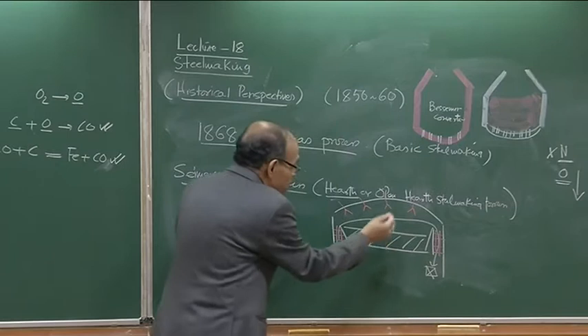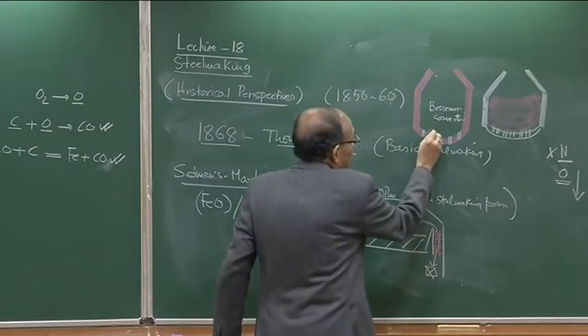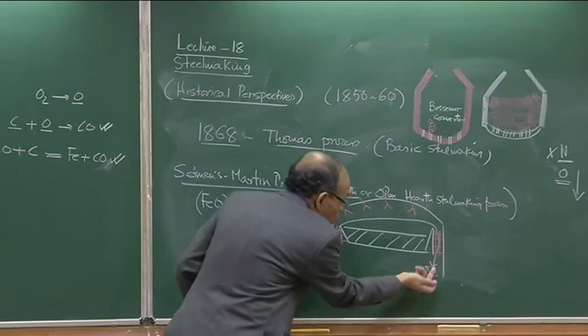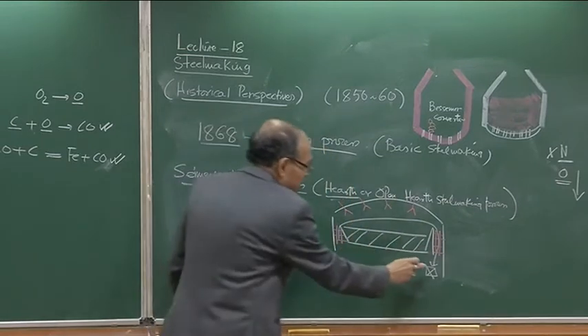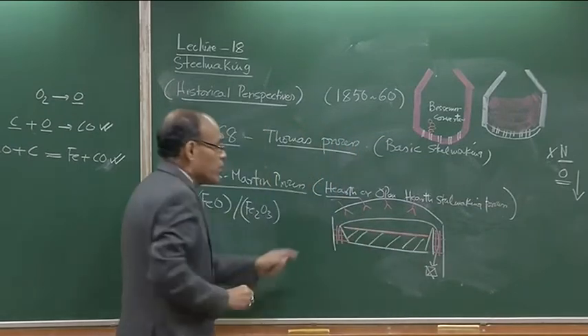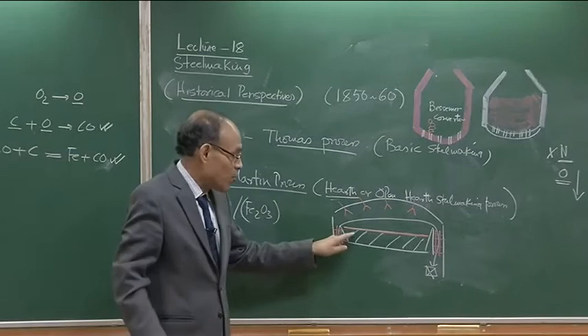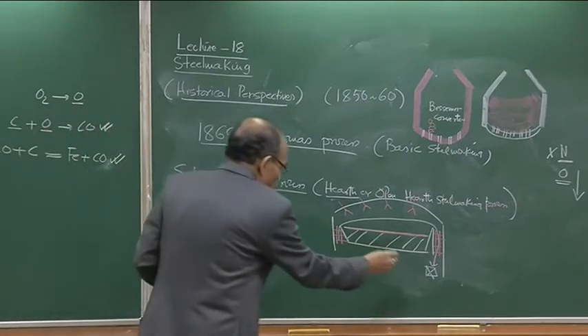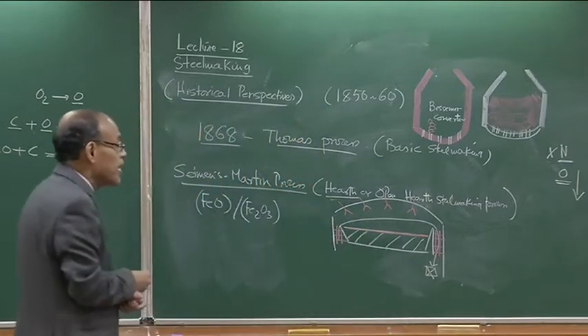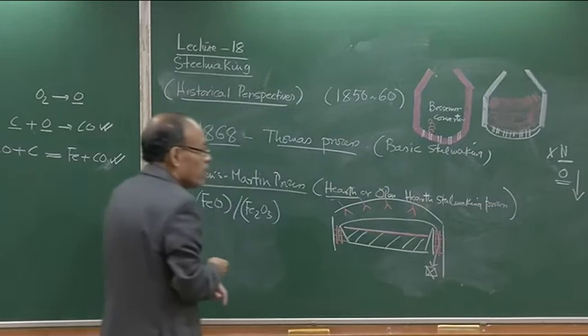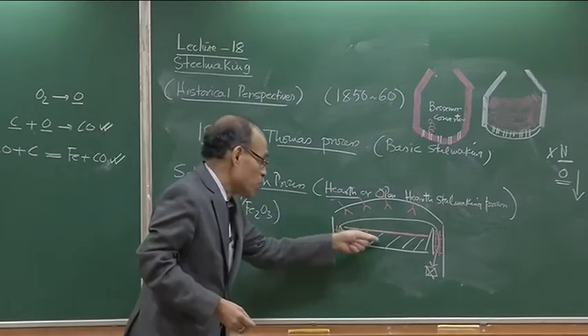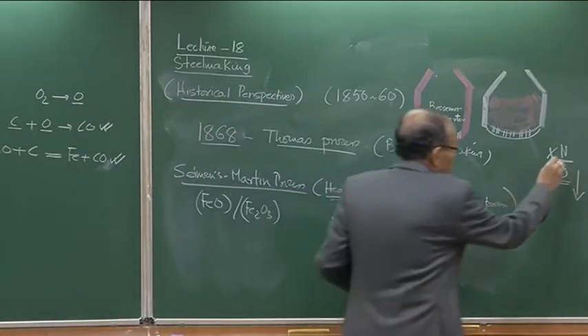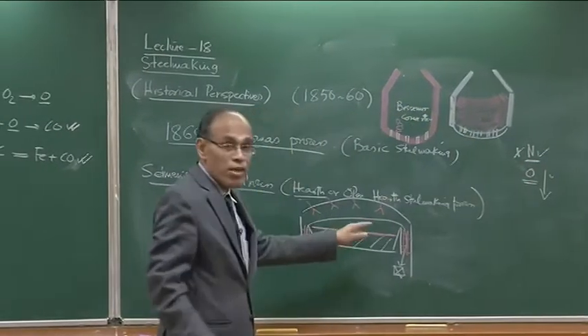Even though you are using air to put heat back into the system, this air has very little scope to react with the molten metal, which is covered by slag. The air contact is at most at the free surface itself. So air does not supply oxygen to the molten metal — it merely advects the heat and makes it available within the furnace environment, where heat gets transported to the melt through radiation only.